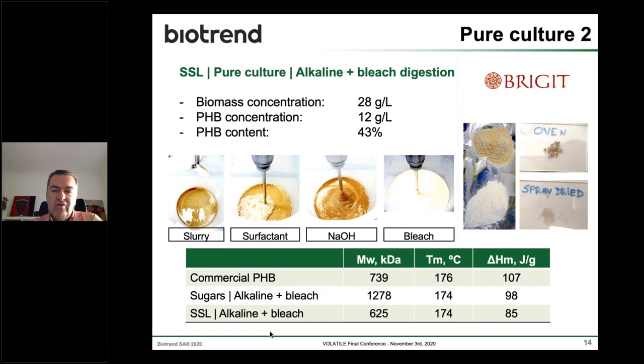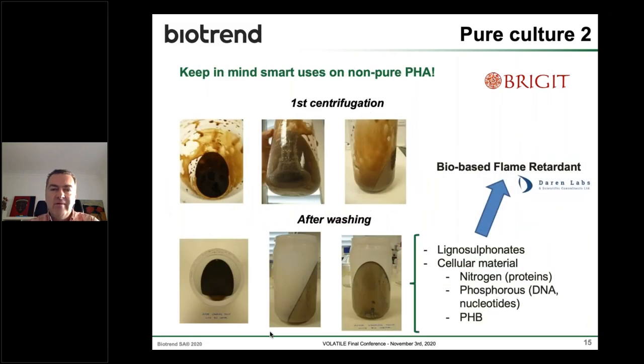And although the purity was not up to our standards, you can see on the bottom table that the molecular weight of the polymer decreased significantly from almost 1.3 million daltons to 600 kilodaltons. So we halved the average molecular weight. So although we had an aggressive purification process, the purity was not too poor. And this brings us to a point, and in some processes, we need to decide what we want to use these polymers for.